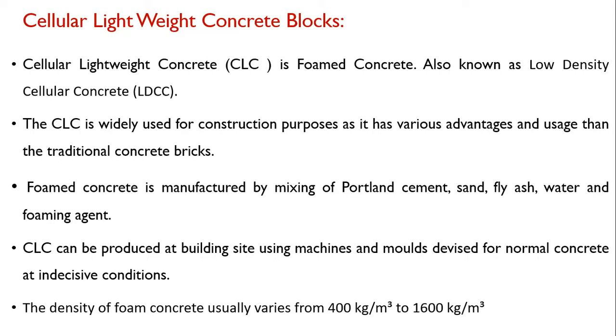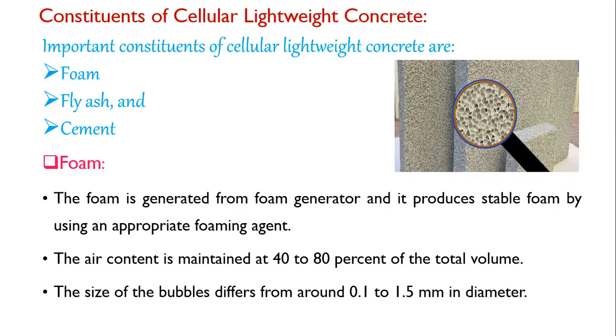CLC can be produced at a building site using machines and moulds — devised for normal concrete — under in-situ conditions where conditions may or may not be favorable. The density of foam concrete usually varies from 400 kg/m³ to 1600 kg/m³.